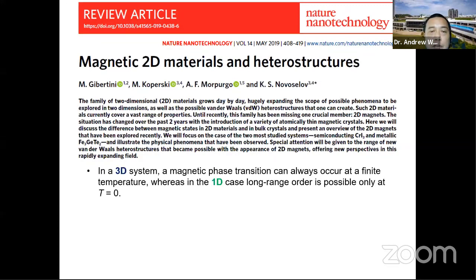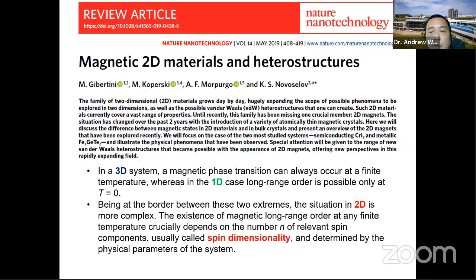So we know that in 3D systems, you can get a magnetic phase transition at a finite temperature, typically a Curie or Néel temperature. But in a 1D system, however, you can't get long range order. You can only get it at T equals 0. So it's difficult to make 1D systems magnetic. In 2D systems, however, it's at the border between these two extremes. So the existence of magnetic long-range order at any finite temperature depends crucially on the number of relevant spin components. This is called the spin dimensionality, determined by the physical parameters of the system. So let me explain what this spin dimensionality is.